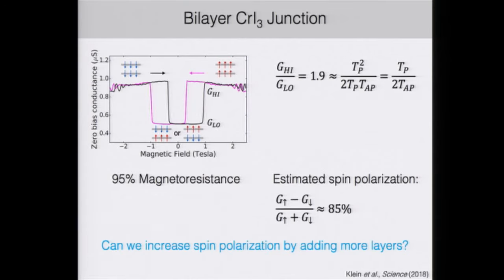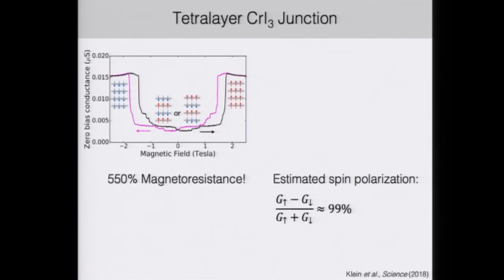So you may be asking the question, can we then increase the spin polarization further by adding even more layers? And the answer is yes. So in a 4-layer chromium iodide junction, we have a much larger zero bias magnetoresistance of 550%. And based on our model, we're estimating that the spin polarization is quite large, up to 99%, though this is an approximation, in this fully aligned case.